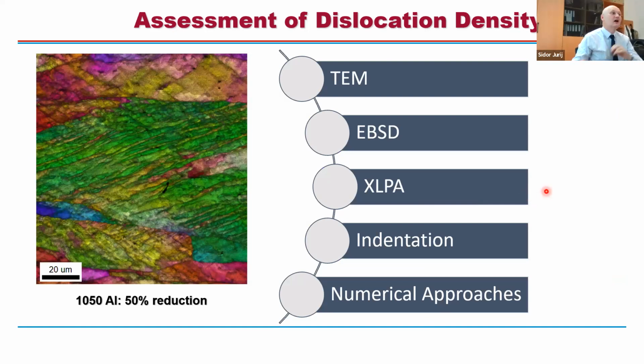The next stage: how to assess the amount of dislocations. So when you deform the material, something is going on inside the material. And this something is the generation of linear defects, which we call dislocations. Here you can see the EBSD of 1050 aluminum alloy. It's a technically pure aluminum alloy, subjected to 50% thickness reduction, and all those features that you see, basically they are created by the movement of dislocations.